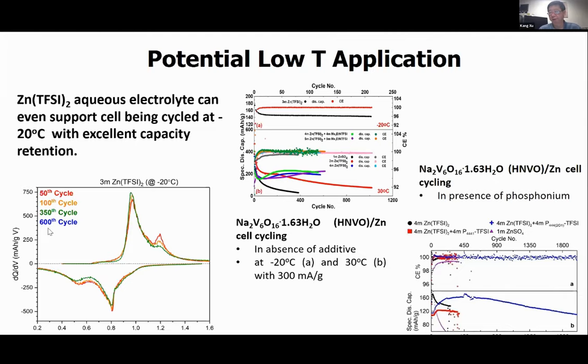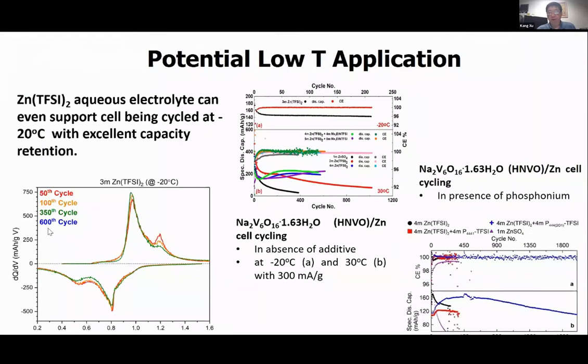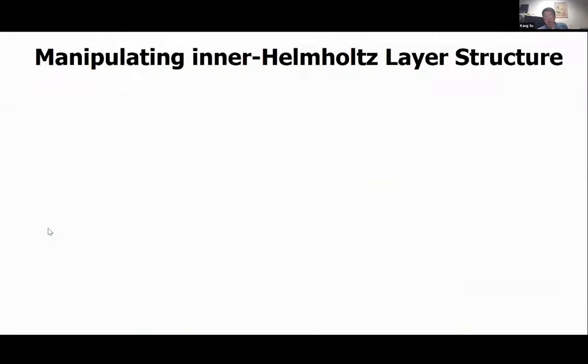So this is universal for those highly concentrated or even low concentrated zinc aqueous electrolytes, because like I said, the water structure is completely broken by the zinc cation, which is working to our benefit. So very likely this could be a very good low temperature electrolyte, which can even be used under temperatures of, you know, an Arctic environment. So we want to further manipulate the inner Helmholtz layer structure.